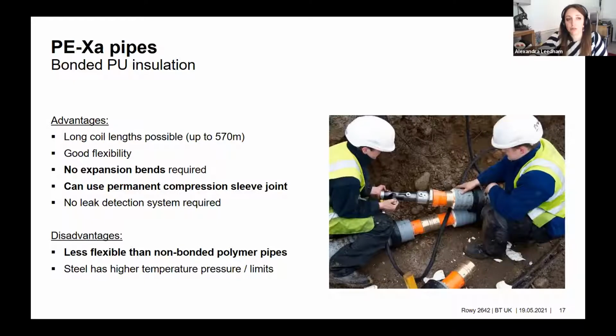So we do two different types of PEX pipes. The PEX pipes themselves are the same, but one is with bonded PU insulation and the other is with layered PEX insulation. The advantages of both is very long coil lengths, so you don't have to have any connections in between 12-meter lengths or 6-meter lengths. So for long soft dig, especially projects where you're not required to open just a short part of a road, for example in a city center, coiled pipework is really energy and time saving. Has really good flexibility and no expansion bends are required. Again, for polymers, these expansion forces are self-compensating as long as you're burying the pipework in the correct manner.